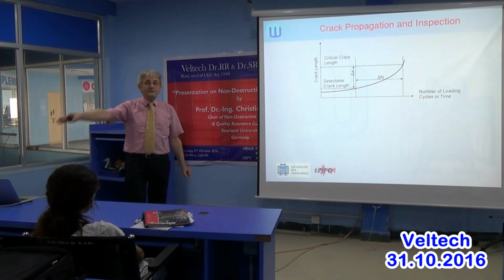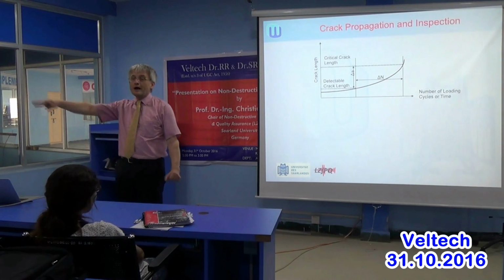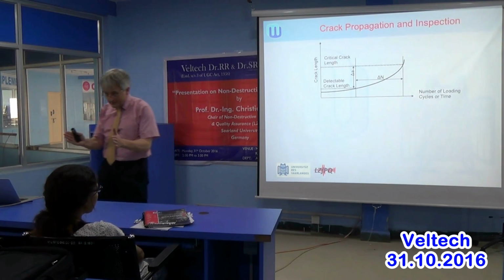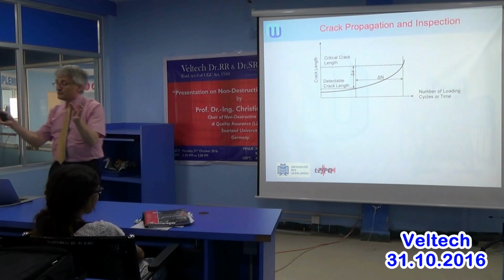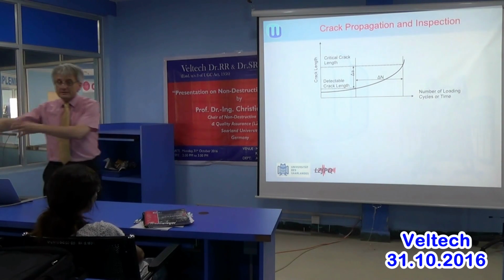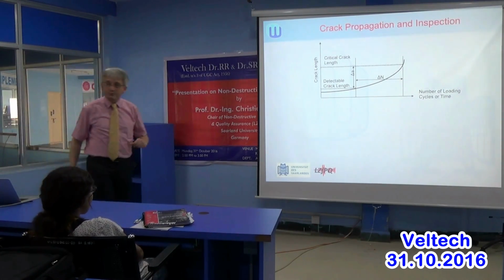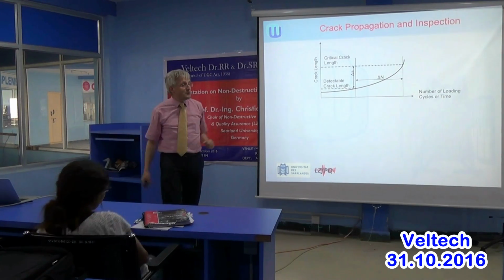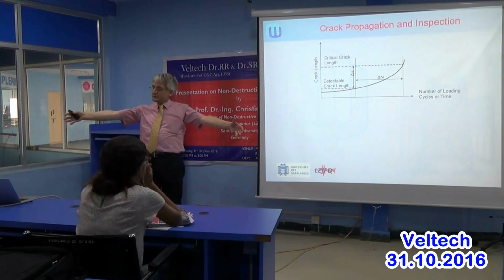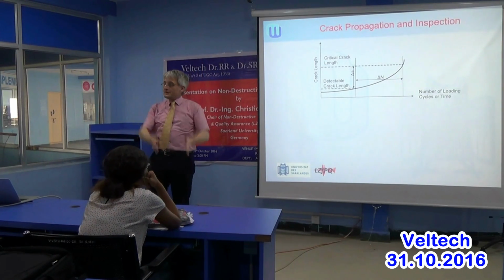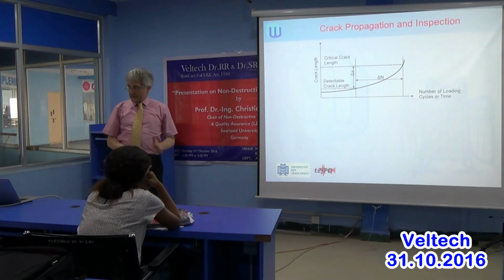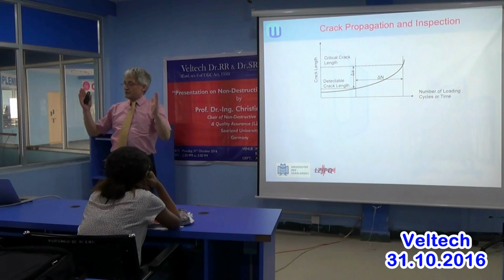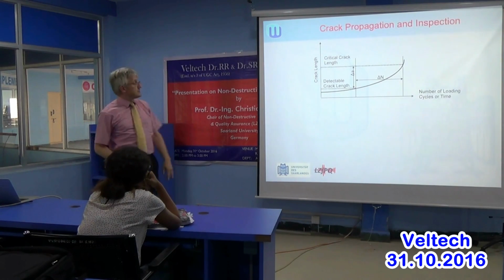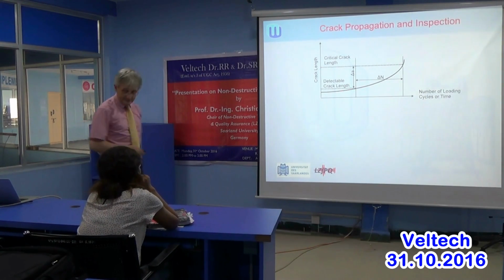So if we would have samples here and all of you would have to see if you see the crack or not, we would have a certain statistical distribution. You might see cracks better than we might, and you may even see better, and you may miss one completely. We would have a statistical distribution, but we would certainly have one crack length where we would say, this one we can guarantee everybody who is trained will see that crack. So that's what we're going to call the detectable crack.